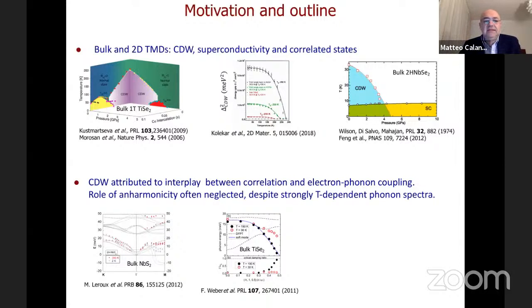So it means that when the system goes below 200 K, it reduces the symmetry and a structural distortion takes place. And when you apply pressure, so you move here, or when you intercalate copper, the charge density wave is destroyed and leaves the place to superconductivity. The system was recently also synthesized in single layer form, or better, in single tri-layer form. I will explain the difference later. And a charge density wave is also found in single layer.